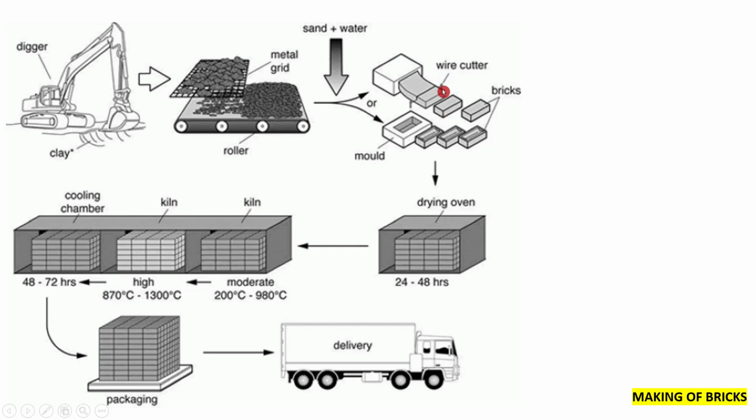So normally this wire cutter method is better because the obtained brick will have higher dimensional stability. That means all the dimensions will be more accurate in the case of wire cutter. Here there will be some shrinkage problems which will change the volume or dimensions of the brick. So we extracted the clay, we made the base material by combining it with water and sand. We molded it. Then we have to